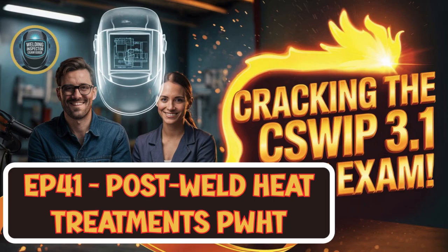And getting that temperature right is critical, I assume. Absolutely critical. It's what's known as an essential variable in the welding procedure qualification, the WPQR. That's the certified recipe for the weld. If you don't control that soak temperature correctly within the specified range, you might invalidate the entire procedure. You might have to requalify it, retest everything. Or worse, the part itself might be deemed unfit for service. Huge implications. Wow, okay, so essential variable. Got it. What's number 3?